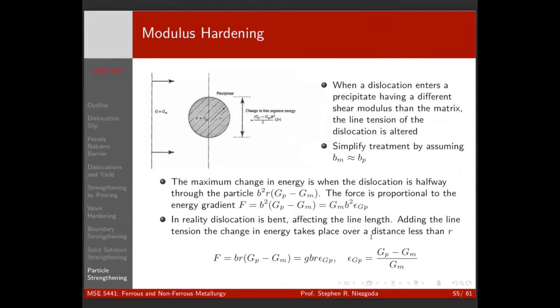Okay. We also have modulus hardening, right? Which is the same argument that we made before. If I have a particle that has a different shear modulus than my matrix, once the dislocation starts to cut into it, it's going to have a different energy than the dislocation in the matrix, right? So that's going to cause the dislocation to either resist going in or want to stay in and cause you to have a bend, right? And so the modulus hardening is the second primary precipitation strengthening effect that we have to worry about, right?